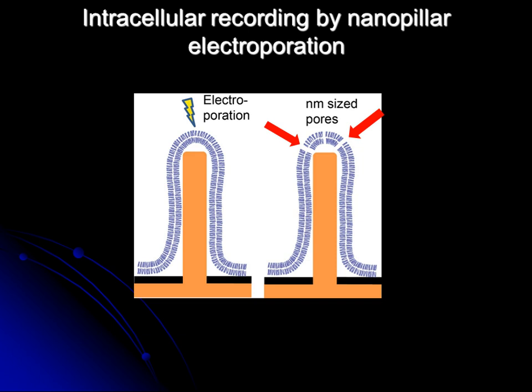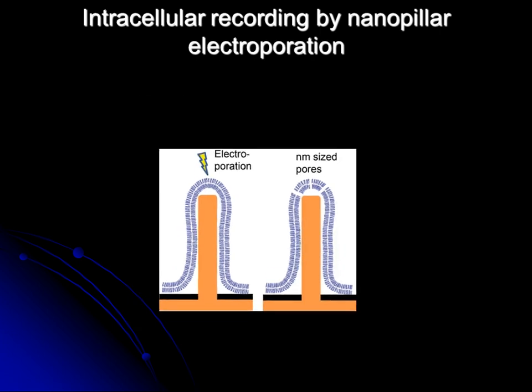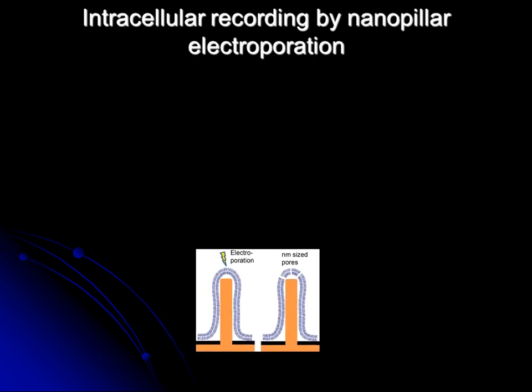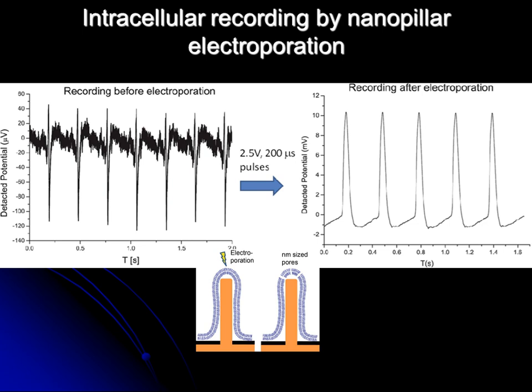That electric gradient will poke holes in the membrane that's in very close distance to the nanoelectrode, so-called electroporation. Electroporation has been widely used by cell biologists to deliver DNAs to the cell. In our case, because the membrane is very close to the electrode and the electrode is very sharp, we do not need hundreds of volts or thousands of volts. Instead, we just need a couple of volts to do the electroporation.